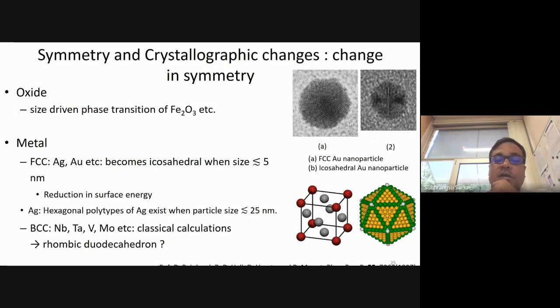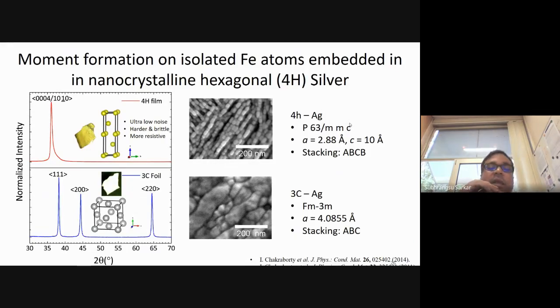In our lab, we worked a lot with silver. The silver that we see every day is shining and white in color, as explained in the bottom panel, and it's termed 3C. The C stands for cubic. In our lab, we were able to grow a different form of silver by electrochemistry. This silver doesn't look white anymore. It looks like pure gold. This silver has extremely low electrical noise. It is much harder and much more brittle than the silver that you find in everyday life. And its electrical resistivity is much higher than normal bulk cubic silver.